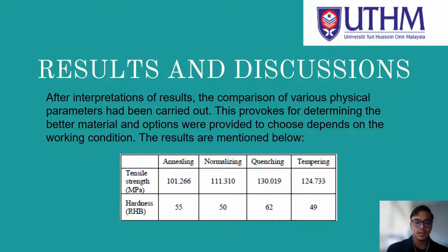Alright, I will continue the results and discussions. After interpretation of results, the comparisons of various physical parameters had been carried out. This helped in determining the better material, and options were provided to choose depending on the working conditions. The results are mentioned below: annealing, normalizing, quenching, and tempering. For tensile strength, for annealing 101.266, for normalizing 111.310, for quenching 130.019, for tempering 124.733. The hardness of the annealing is 55, for normalizing 50, for quenching 62, and for tempering 49.